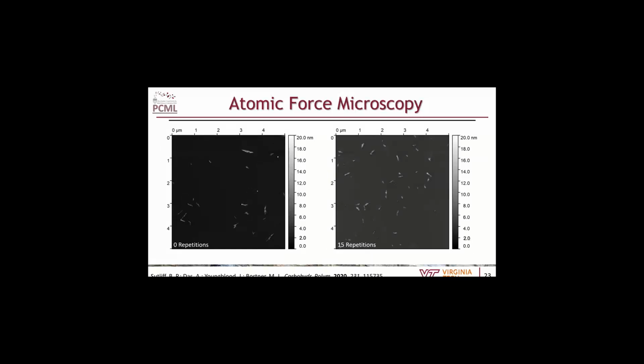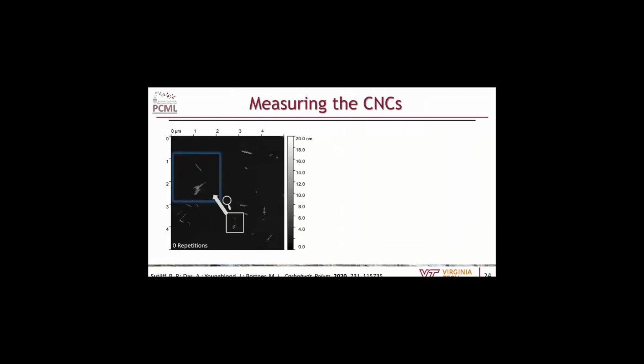If you look quickly, there's not much of a visible difference between 0 repetitions and 15 repetitions. But if you take one single cellulose nanocrystal from each of them and you take the height profile along the length of it, you'll have the length of your cellulose nanocrystal from where it drops off on either end, and you can average the sort of plateau region for your average height.